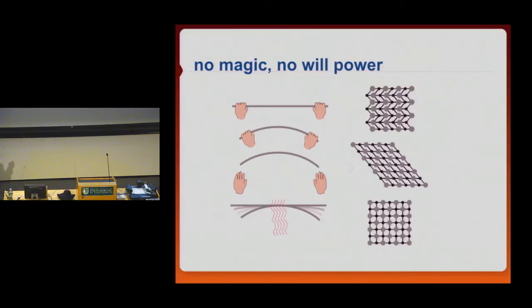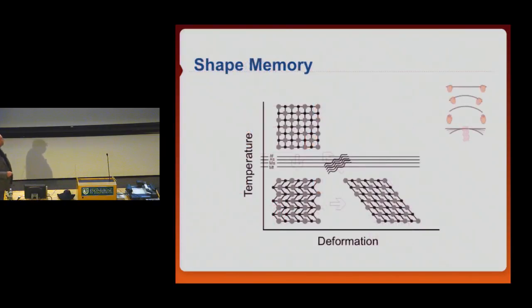When he deforms this rod, he detwins the twins, and when he heats it up, the material transforms back into austenite, which at this temperature is the stable phase in this particular system. So we can clearly state that he used the shape memory effect of whatever alloy, most likely Nitinol, might have been something else. And here we have the full cycle of that.